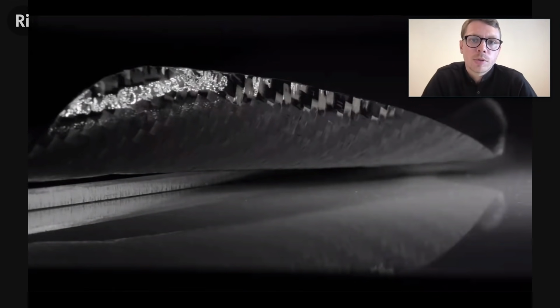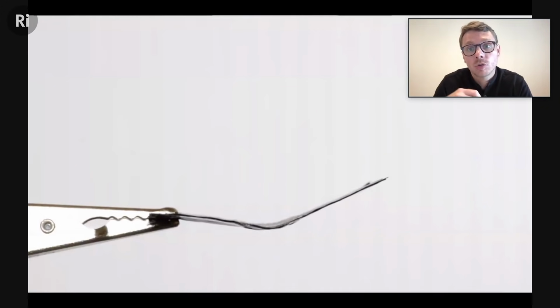Another material that we've explored is composites. So carbon fiber or fiberglass or Kevlar. We collaborated with a company called Carbitex, and they make fully cured but flexible carbon fiber. So it's really innovative in that it's highly strong, it's lightweight, but it's fully flexible. So we can make active carbon fiber, in this case, by printing on it, or you can bond or laminate to it. Basically, we add different polymer layers to the composite, similar to the wood, we create different grains.